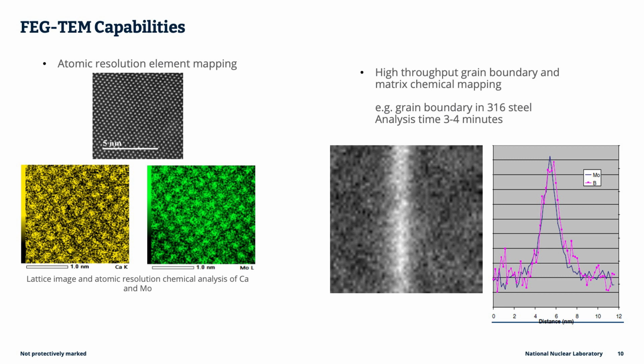When we were out getting the demonstration on the JEOL, we took with us a waste form sample where originally it had been believed this was a glass, but we found these crystalline areas in it. We're able to produce these atomically resolved EDX maps showing the co-location of calcium and moly in the crystal structure in that. The right-hand example there is a grain boundary in stainless steel, which we mapped with EELS, and the results there are on the right-hand side, although there's no vertical scale, shows you that the moly and the boron are enriched at those grain boundaries, very much the same spatial distribution.